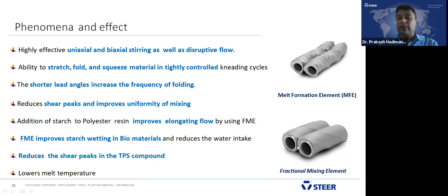Now the function of the FME. The addition of starch and polyester resin improves the elongational flow by using FME elements, and the fractional mixing elements improve starch wetting with the PBAT and the biomaterials and reduce the water intake into the final compound. It also reduces shear peaks in the TPS compounds and lowers melt temperature, increases the miscibility of the final product and increases mechanical properties. And in the morphology study, we observed better dispersion of these two blends by using melt formation elements and fractional mixing elements.